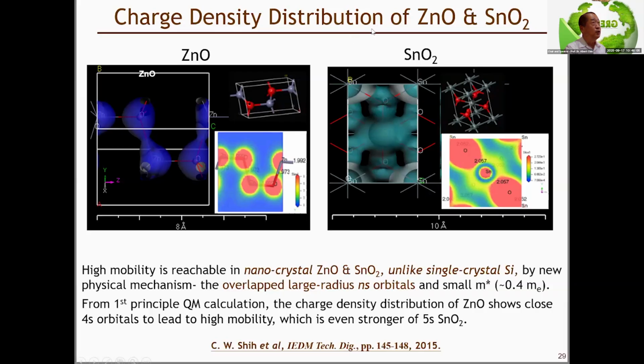Here shows the charge density distribution of the metal oxide. The high mobility is still visible in nano-crystal metal oxide, unlike the single crystal silicon. By a new physical mechanism, the overlapped large radius ns orbitals and the small effective mass. From the first principle quantum mechanical calculation, the charge density distribution of zinc oxide shows close 4s orbitals that lead to the high mobility. So that's the reason for the high mobility, which is even stronger in 5s tin dioxide. So we reported this result in IEDM 2015.